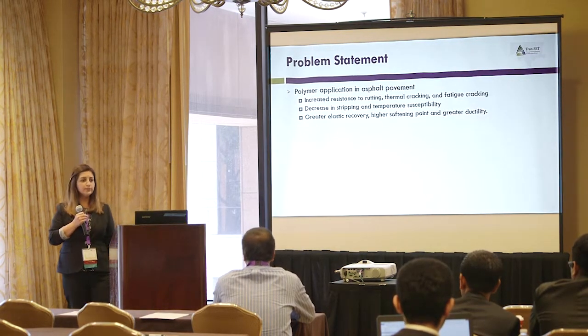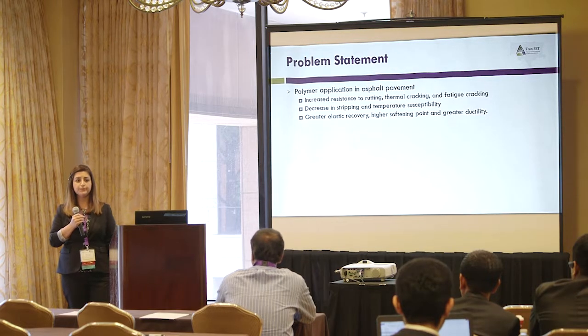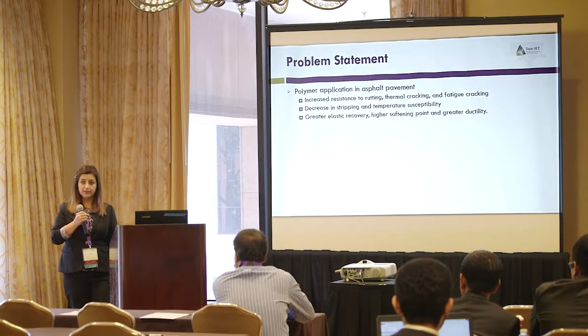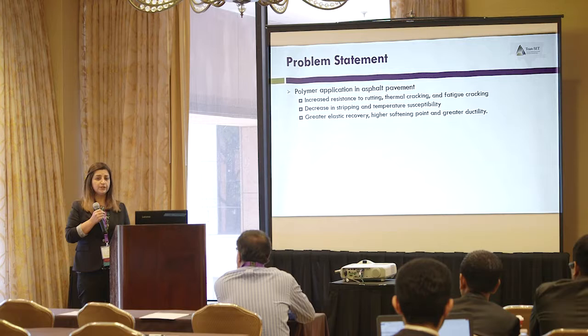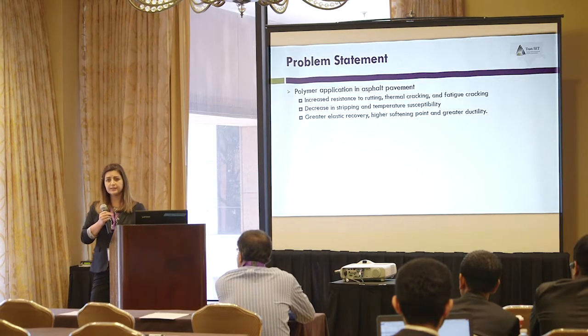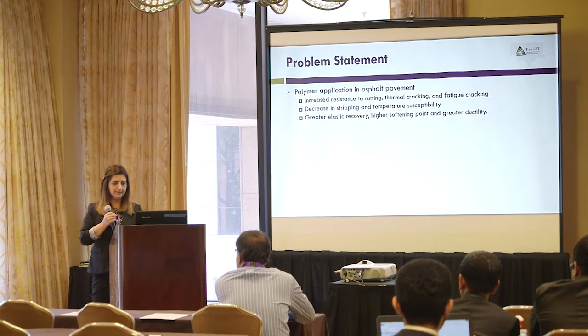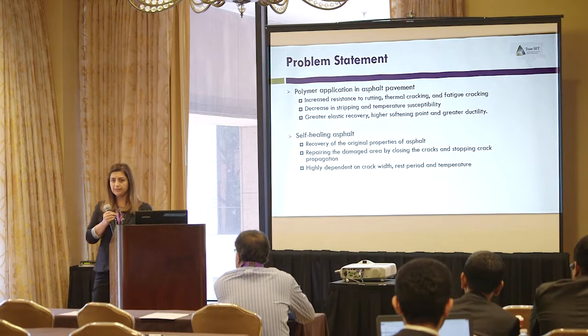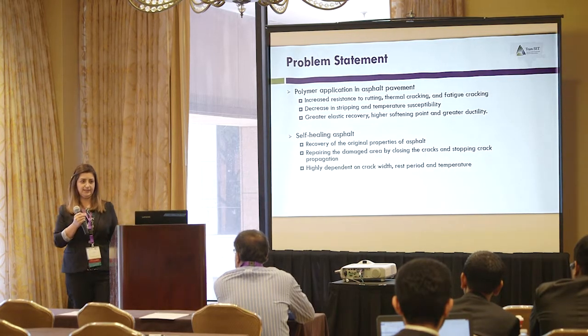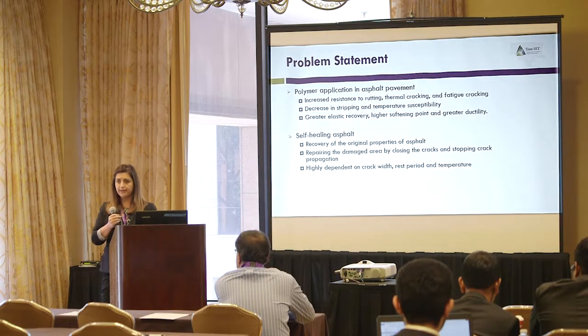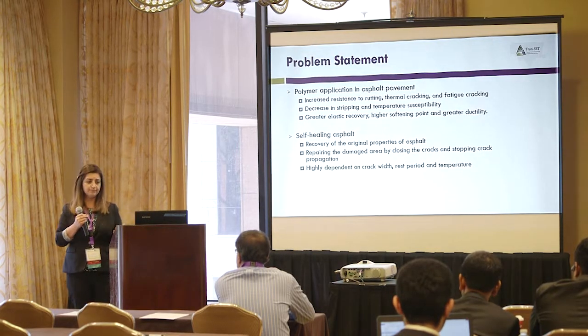During the last decade, polymer modifiers were used to improve elastic recovery of the binder, to increase rutting resistance, cracking resistance, and thermal cracking resistance. Also, asphalt binder has self-healing ability, which means it has the ability to recover its original properties with rest period and temperature.